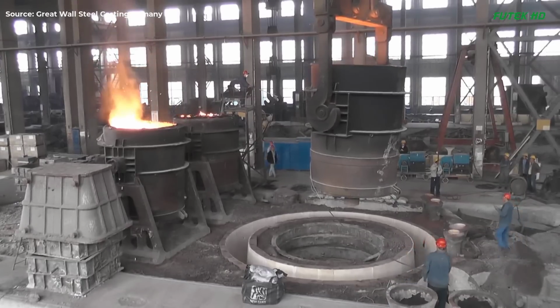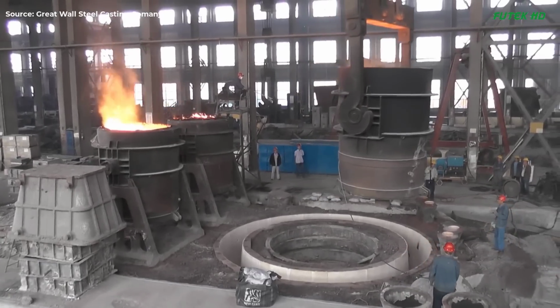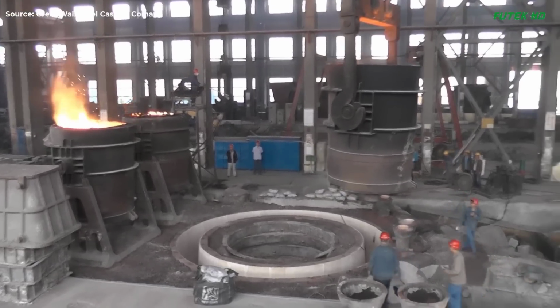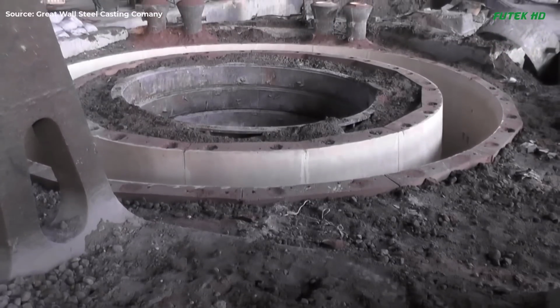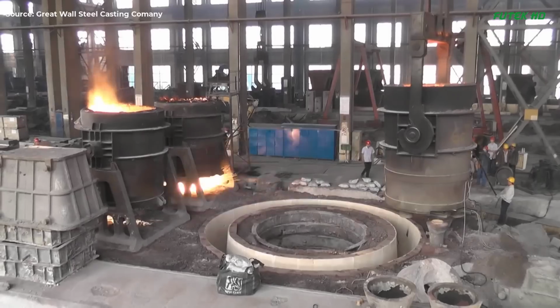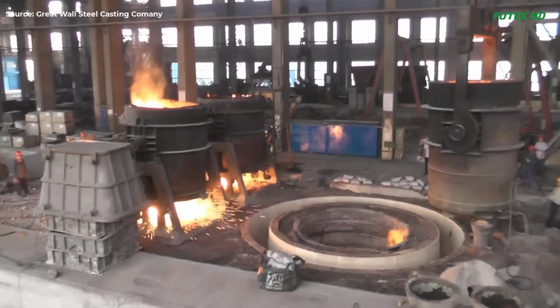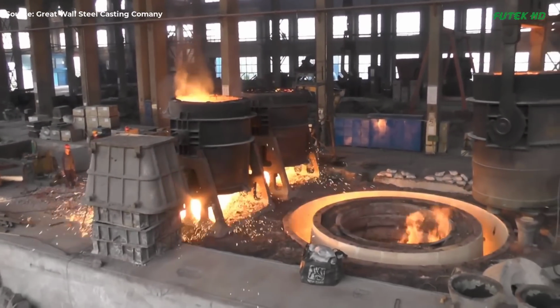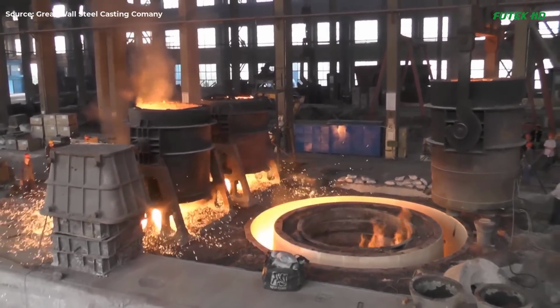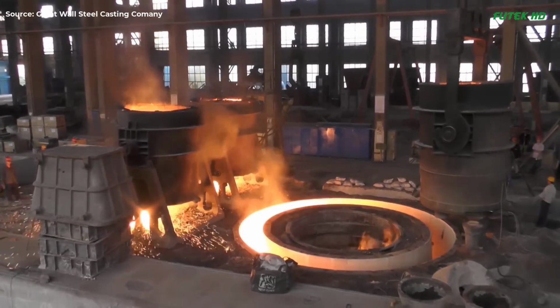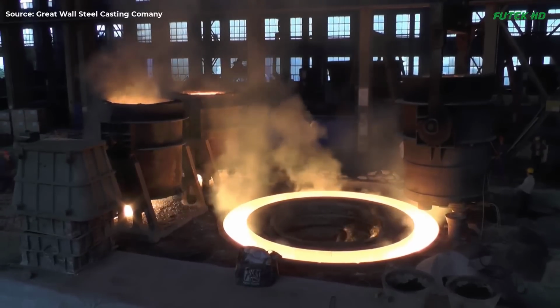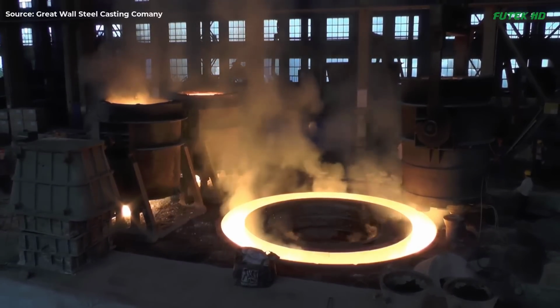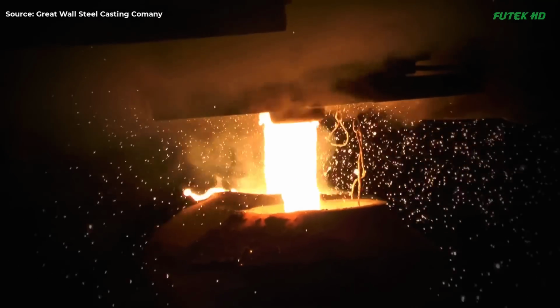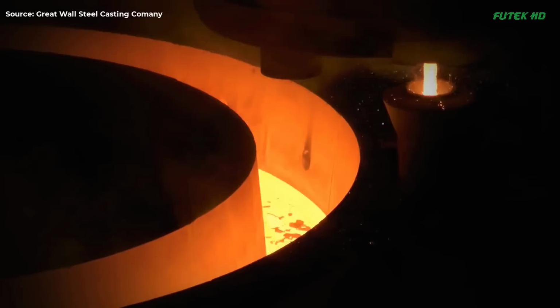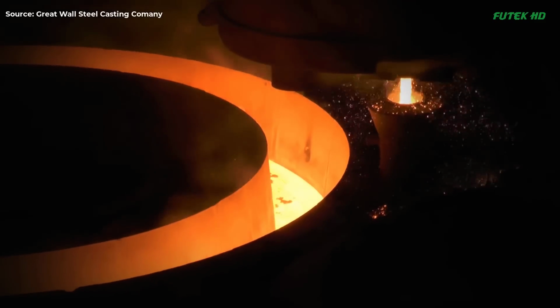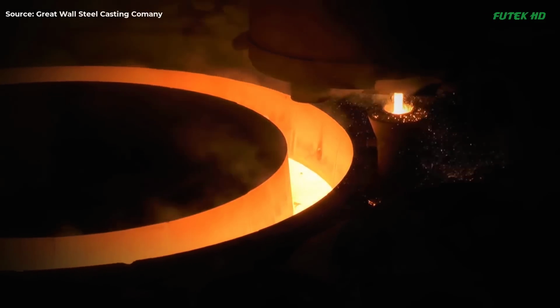The heat treatment process is crucial for achieving the desired mechanical properties. The slag pot is heated to a temperature above Ac3, followed by austenitizing at approximately 915 degrees Celsius. Controlled cooling in the furnace ensures proper structure formation. An intermediate holding phase occurs at 600 degrees Celsius to 630 degrees Celsius, with cooling completed in the furnace down to 300 degrees Celsius. This precise temperature control ensures the slag pot's durability and performance under extreme conditions.